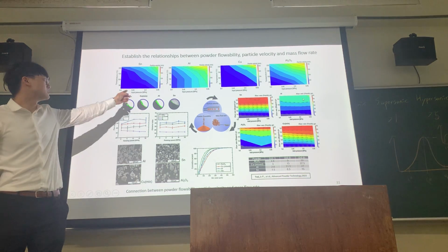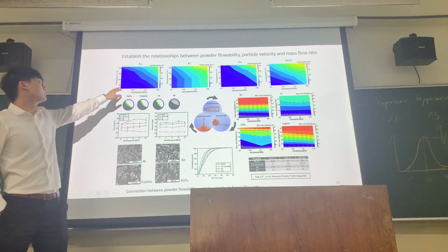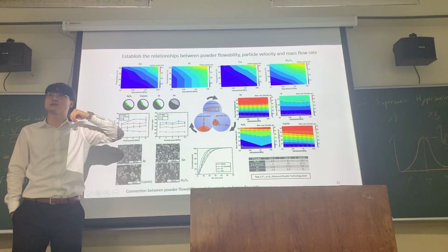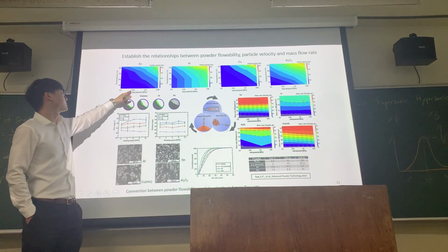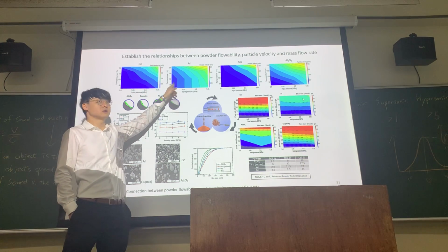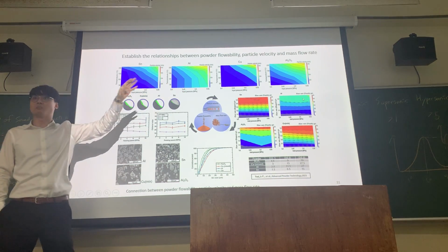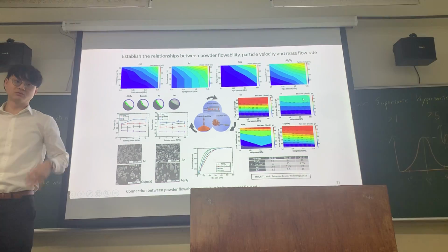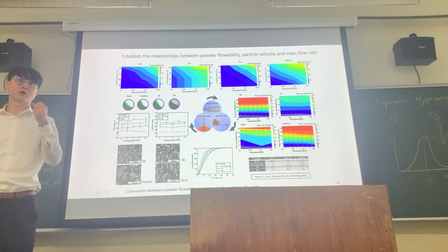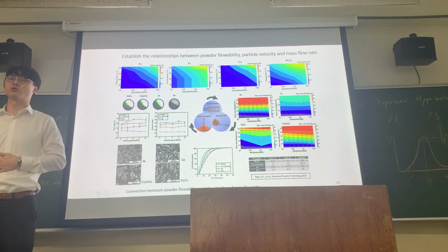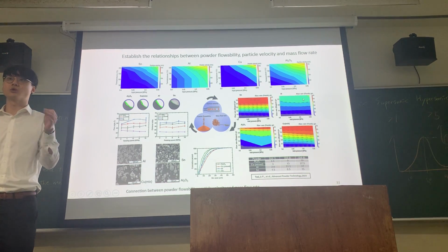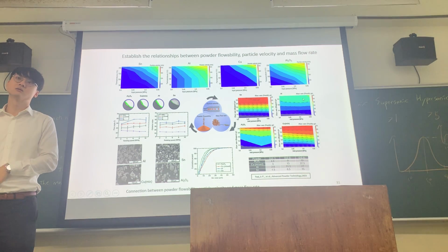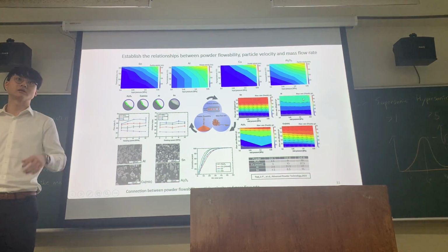You can see by evidence these colorful gradients that I'm showing are the particle velocity, right? At a fixed parameter, each of these results is different. The particle velocity is very different. So again, don't assume that if you fix on a certain process parameter, the output is going to be the same if you input different materials. Does that make sense to you guys? Are you familiar with that?